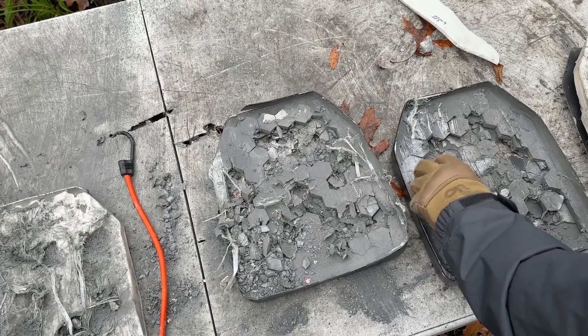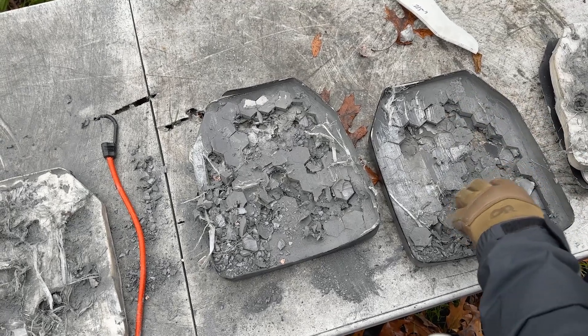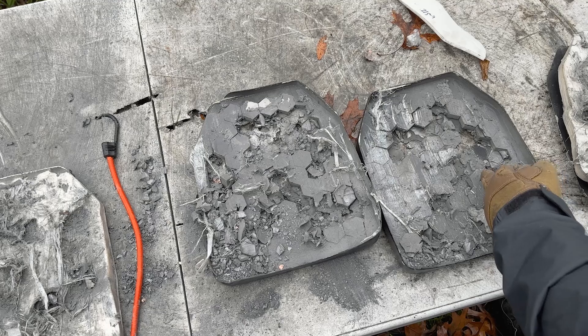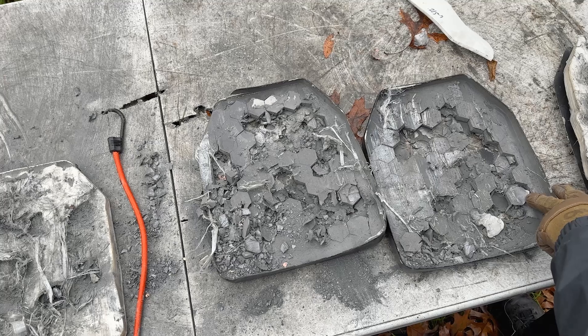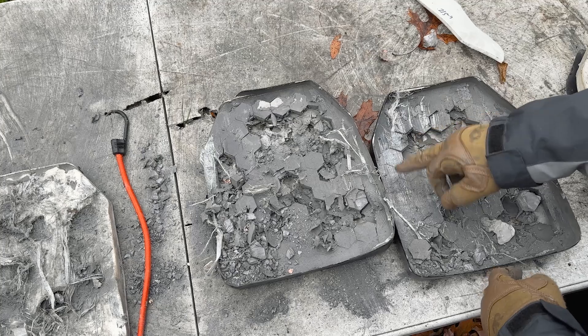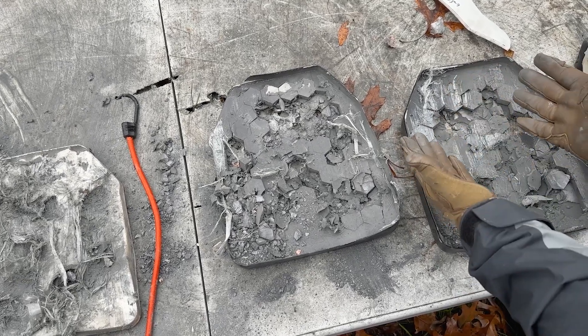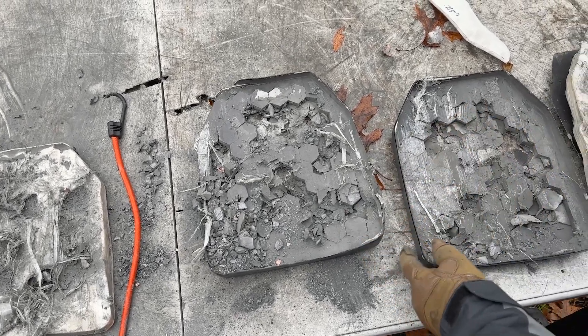This is the advantage of a tile array plate — look at how much of the tiles remain. One disadvantage is if you can't have these little hexagon tiles cut to a certain size, you have this foam ring on the outside. I measured that right around 794 thousandths, and it is a little more in some areas depending on where the mosaics end. This whole side of the plate was left relatively intact. The backer and front side did come apart fairly easily after all those hits — I would like to see some better adhesion there — but otherwise pretty solid.